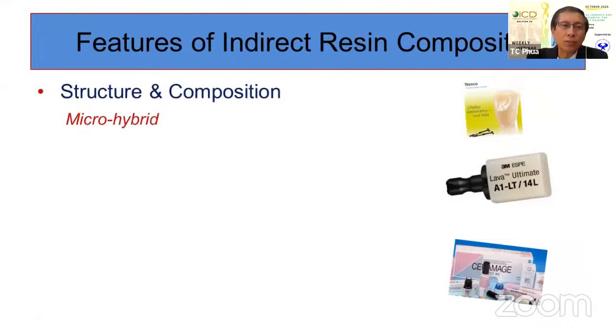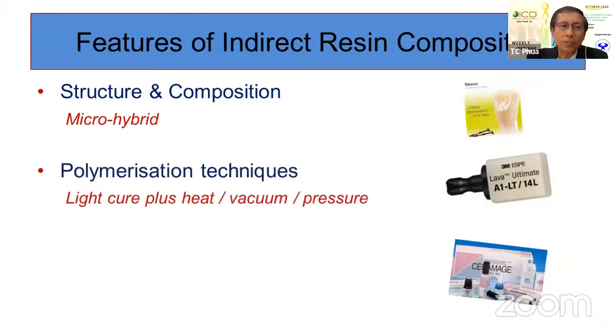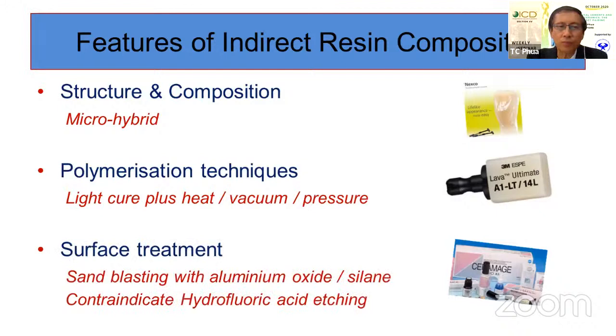So here we have some representation, as I say, Nexco, Lava Ultimate, Ceramage. So the structure and composition is essentially a microhybrid type of composite. The polymerization techniques can be light cure plus heat, vacuum or pressure. Surface treatment is oftentimes sandblasting with aluminum oxide, and silane. It's contraindicated for hydrofluoric acid etching, because there's not much glass in it.